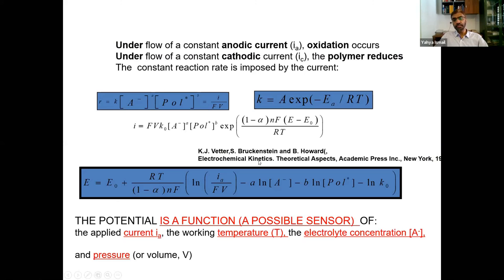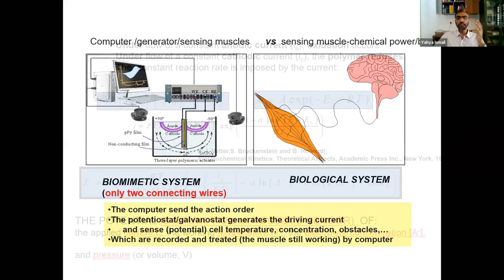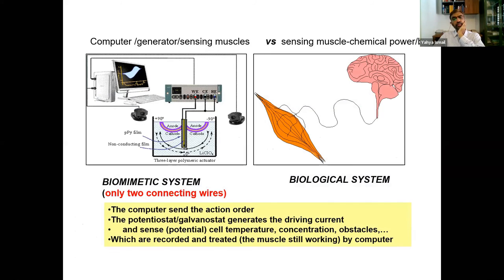The theoretical modeling is a little bit complicated, because in the famous Butler-Volmer equation, there is an activation energy term. These energy terms are derived for dilute systems. When you apply them to condensed systems, like polymeric long-chain molecules, you need certain energy to relax the polymeric chains. Those aspects were not there when the theory was developed 100 years ago. So we developed a theory to support this.